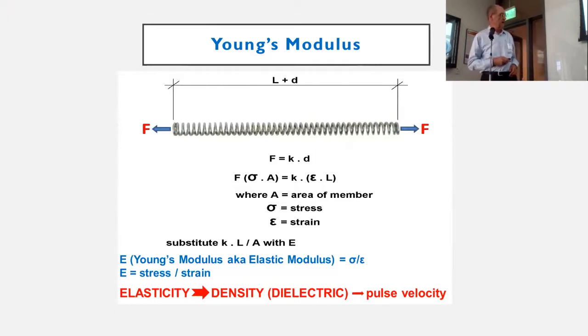Finally, I'll also show you a piece of equipment where we use pulse velocity. Pulse velocity, again, is a sound wave that we send through material and then pick up the image. And with that image that we pick up, we'll know what the speed of the pulse velocity was through that. For instance, in concrete, the average velocity of sound is about 12,000 feet per second. Knowing how thick the member is that we're looking at, and I'll demonstrate with the equipment, it'll be easier to figure this out.